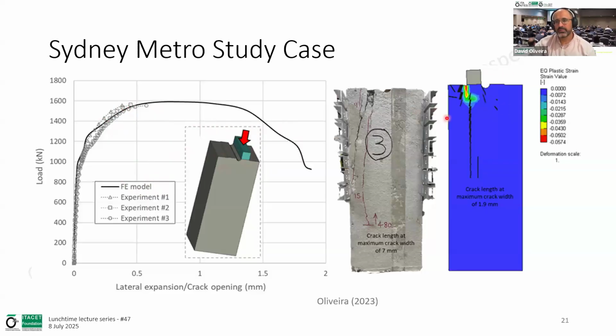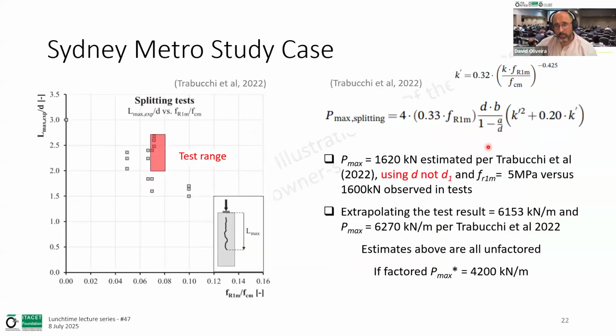And we were quite satisfied that, again, our model was representing very well what we observed in these tests. Now, comparing what the model by Trabucchi would predict for these tests, we were actually pleasantly surprised that the semi-empirical model by Trabucchi would predict in the order of 1620 kilonewtons, while the test, if you remember, was about 1600 kilonewtons. But there was an interesting aspect here.